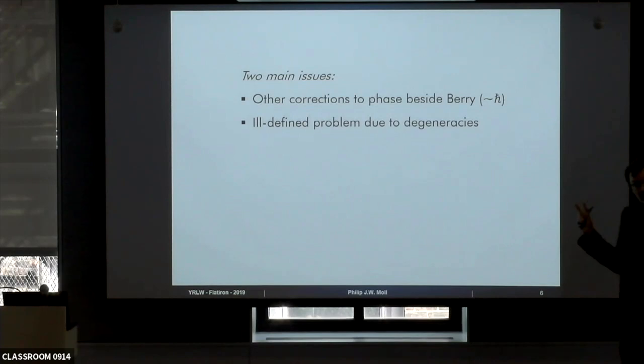You have to remember that Lifshitz-Kosevich was done at a time when we tried to understand the Fermi surface of aluminum, copper, right? So there, if you have, let's say, a centrosymmetric metal that's non-magnetic, then the only degeneracy you have is a twofold degeneracy due to spin. That gives you a twofold degenerate state, and those degeneracies you can trivially take out of Lifshitz-Kosevich. This is what people call the spin damping factor. It's basically summing over two degenerate orbits, you get different phases for the different spins, and you can pull this out, and you eliminate this nasty phase of the Zeeman term from the Lifshitz-Kosevich equation, and you call this just the spin damping factor. Here we have more.